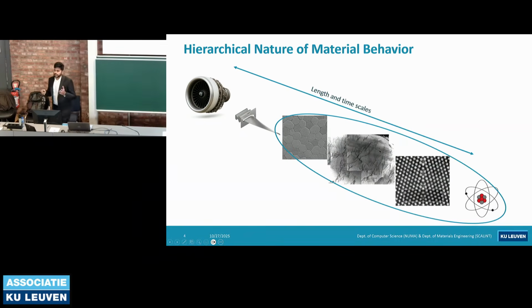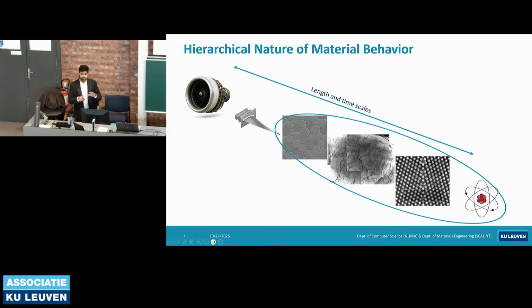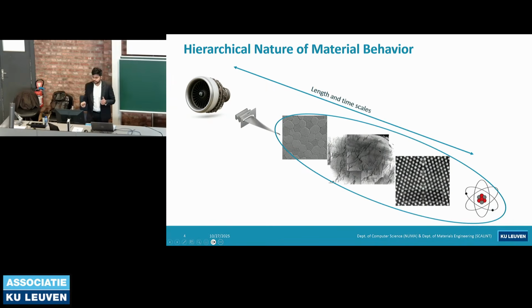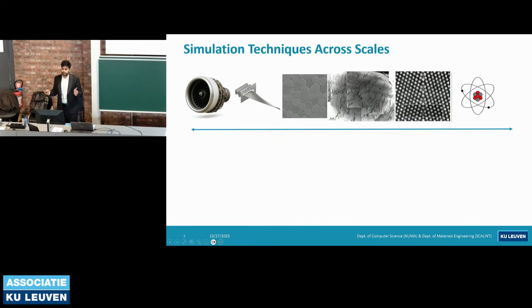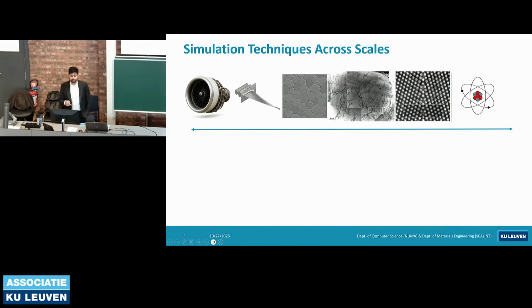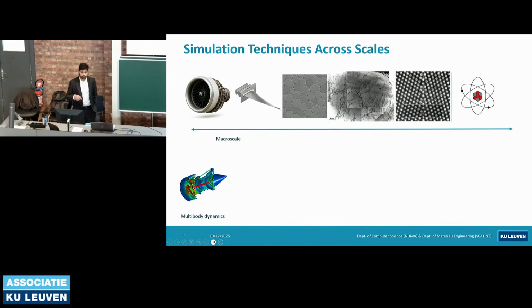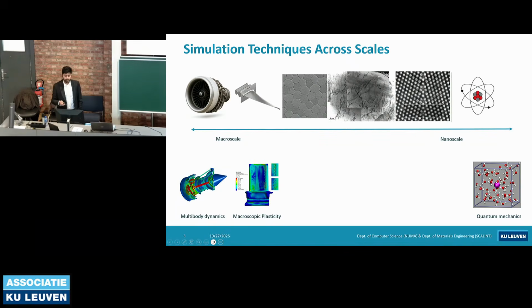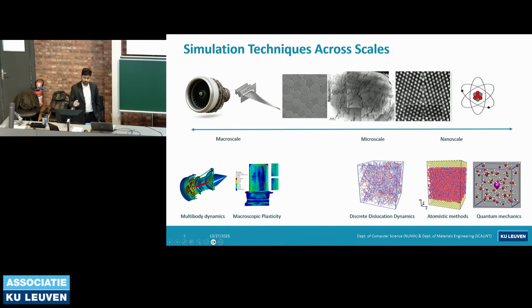So when we are speaking about the mechanical properties of a turbine blade, we are actually referring to the incredible hierarchy of microstructural features that we see here. Since different features are seen at different scales, different simulation techniques are involved to simulate the effect of these features. At macro scale, you have multi-body dynamic simulation, which usually considers the connection between different components. If we look at a single component, we have macroscopic plasticity simulations, which are based on yield functions and plasticity theories. On the other end, where the electronic structure of the material is considered, we have quantum mechanics simulations, and then there is Newtonian mechanics, which does not consider the electronic structure, and we have discrete dislocation dynamics simulation at microscale, which only considers the dislocations and their impact on hardening.